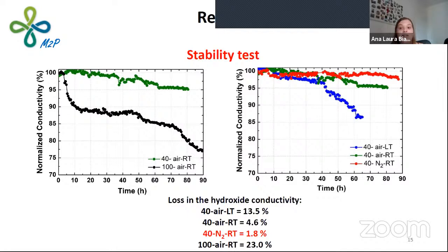So it's possible to attribute such stability to the ETFE backbone that underwent fewer scission reactions and more cross-linking during irradiation when irradiating in an inert atmosphere. Therefore, the switch from air to N2 for inert atmosphere during the irradiation process can provide more reinforced and stable membranes, as well as a higher degree of grafting using lower absorbed doses or shorter grafting reaction times.